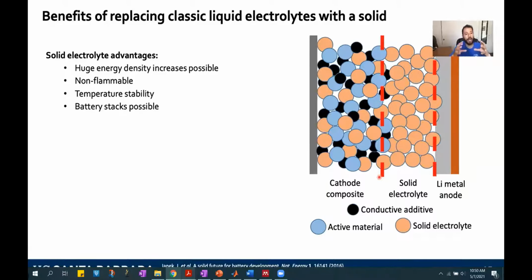And finally, it's that battery stacks become possible. So in a liquid electrolyte, we have to individually package every cell because we don't want our liquid electrolyte leaking out. Here we have no liquid and therefore no leaks are possible, which means that we can start to layer batteries on top of one another and have more sort of module level energy density. Now we need some certain properties from these solid electrolyte materials. The first of which is a high voltage stability, which means we want to be able to be chemically stable against both our cathode side and our lithium metal anode side.